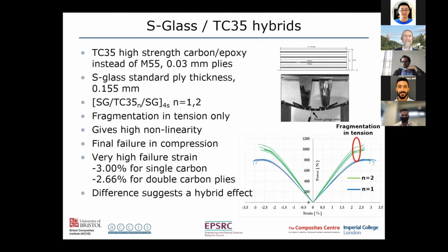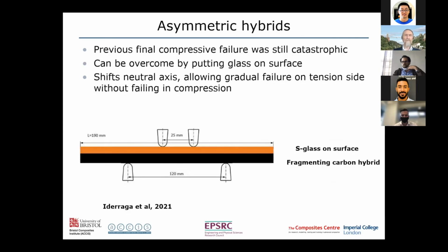Nevertheless, although we've got a large nonlinearity, quite a lot of pseudo-ductile response, at the end of the test it still fails in compression. So what can we do about that? Well, one thing we can do is to put some glass on the surface and make an asymmetric hybrid. So now we have S-glass on the surface, and then we have a fragmenting carbon hybrid here. We can still get the gradual response in the carbon, the fragmentation and the gradual failure, but avoid the catastrophic compressive failure occurring on this surface. So putting the glass there shifts the neutral axis and then allows this gradual failure here without getting a compressive failure.